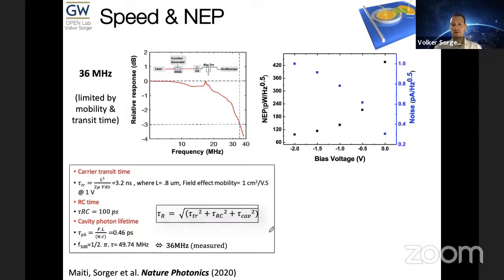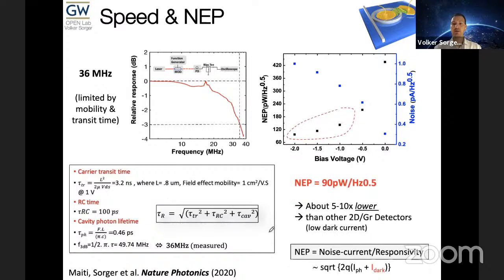The noise equivalent power, NEP, is the power to get a signal to noise ratio of 1 at 1 hertz. So lower is better, obviously: less power to get to an SNR of 1 is good. And we notice here we just need 90 picowatt per square root hertz. This is about an order of magnitude lower than for graphene, simply because the NEP is proportional to the dark current. So lower dark current is great.